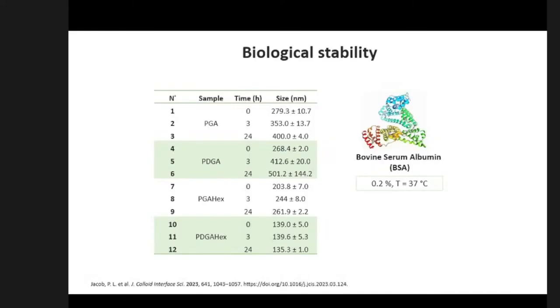Biological stability of the nanoparticles was evaluated by incubating each suspension in a solution of bovine serum albumin (BSA), used as a model protein, at 37 degrees. Hexandiol-based polymer sizes were pretty much the same, and in particular, PDGAHex nanoparticles were the most stable because the hydration shell creates an efficient steric hindrance against BSA.